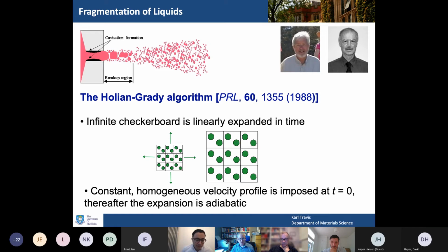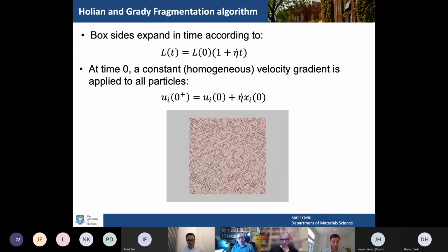So what's this algorithm? Well, you take a periodic simulation box. Here it's illustrated in two dimensions, fully periodic, and you simply undergo uniform dilation. So you stretch it. You do that by imposing a velocity profile at time 0, and thereafter the expansion's adiabatic. You grow the box lengths. In this case, it's a square cell, so each side length is the same, as a function of time. So you take L of t is the original time 0 box length, and you multiply it by 1 plus eta dot t. Eta dot is the strain rate.